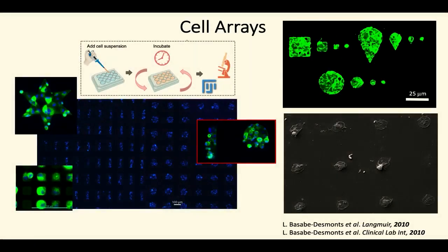If we take those substrates that have been patterned with proteins and we incubate with cells, cells actually will interact with whatever is in the substrate. They see the BSA, they don't like it, they don't adhere, but they see the fibrinogen and they have higher affinity for fibrinogen than for BSA, so they go directly to the fibrinogen. In this case, what you are seeing there is platelets adhering to the fibrinogen patterns, or fibroblasts adhering to fibronectin patterns. And what you see here is that we have good control on where the cells are adhering, and also on how many cells are interacting together. We can go from single cells to a number of cells together. So we can control cell-cell interaction.